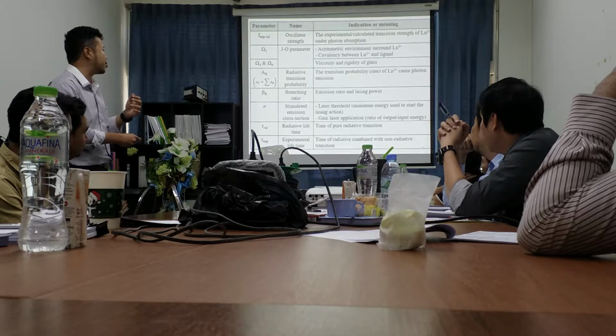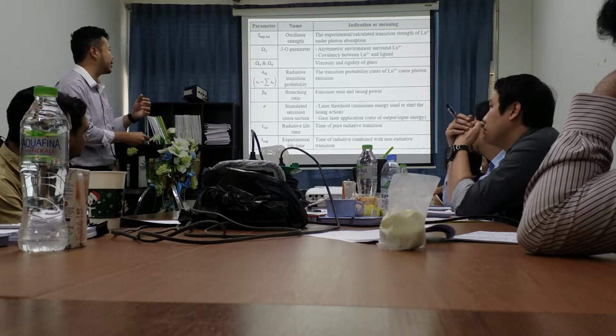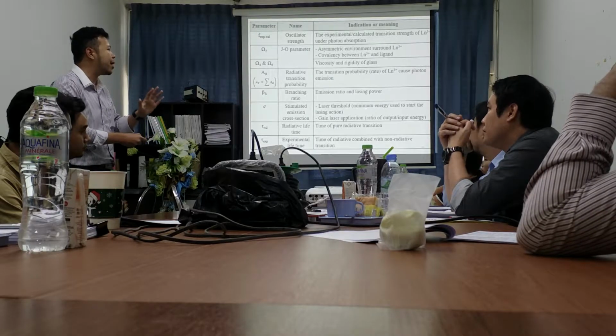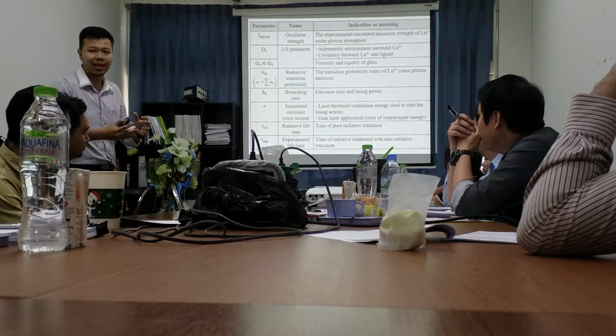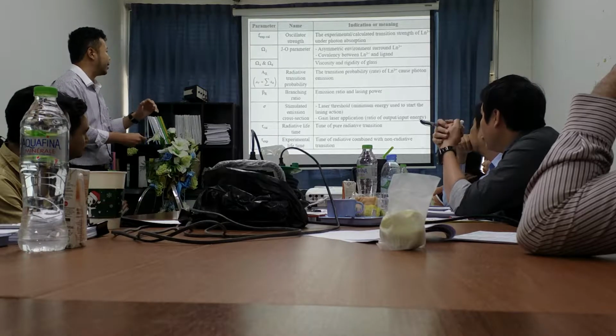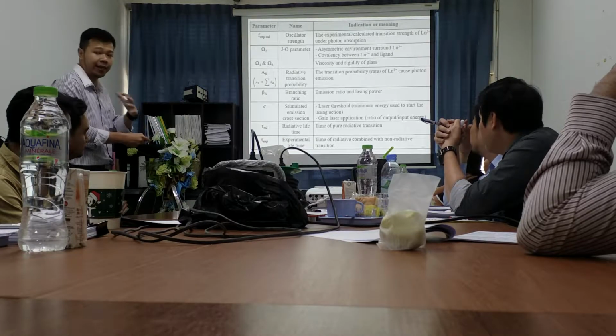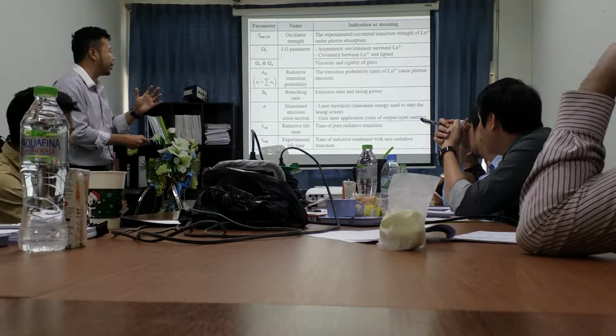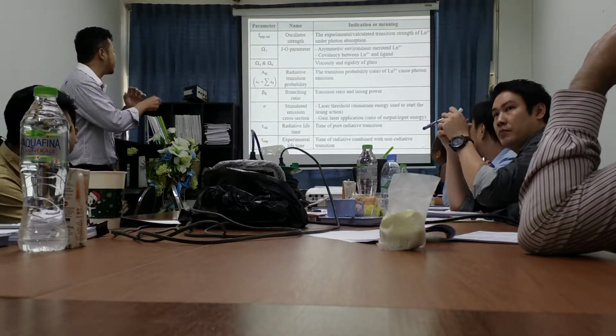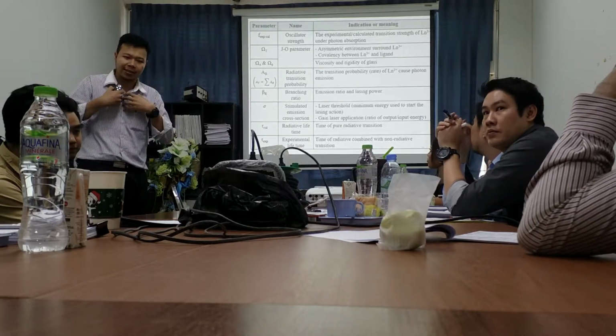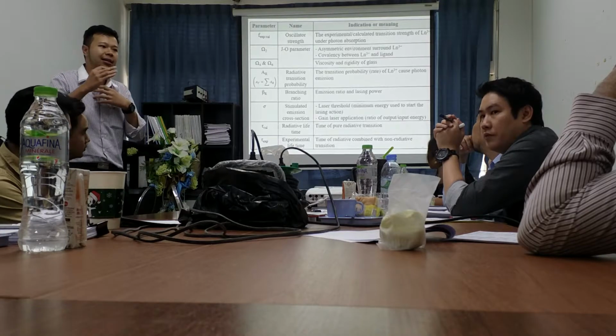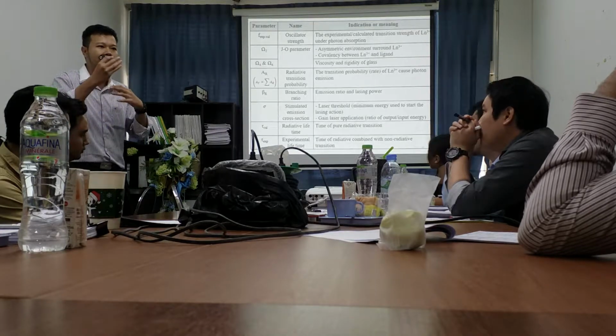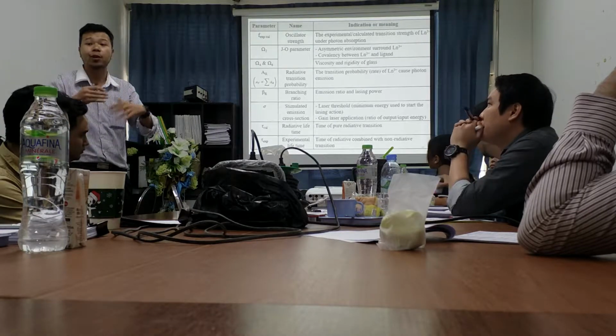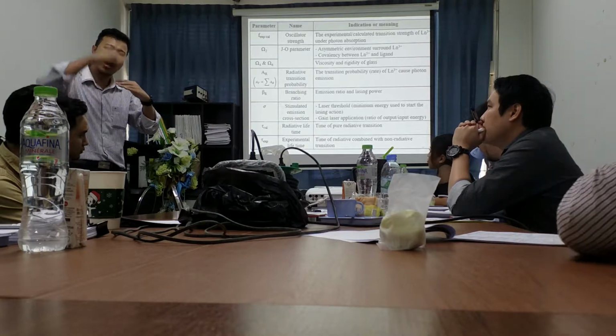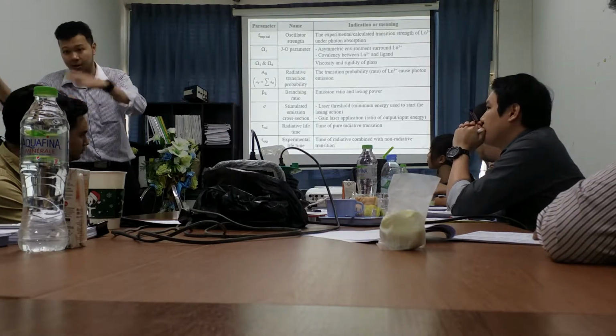Sigma, the stimulated emission cross section, gives us the laser threshold. It is the minimum energy used to start the lasing action. This is important. And it also tells us briefly about the output per input energy ratio. This value doesn't give us the exact value, it's just an approximation, and it just tells us the degree when we compare with other glass. It just tells us about higher or lower when we compare with other glass.